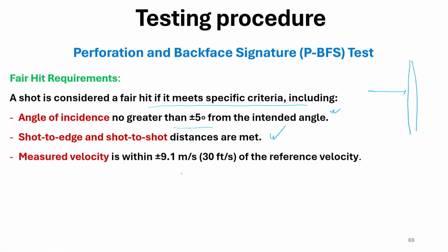Velocity is within 9.1 meter per second of the reference velocity, plus minus 9.1. There are different reference velocities and it should be within plus minus 9.1 meter per second. So, speed should not vary by more than about plus minus 30 feet per second. It should be within the shot to shot and shot to edge distance and the angle of incidence. Then, if it is there, the shot parameter will be considered in the next stage. So, first we assess whether the hit is to be considered or rejected. That is actually assessed by fair hit.